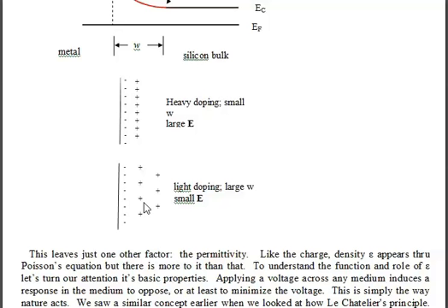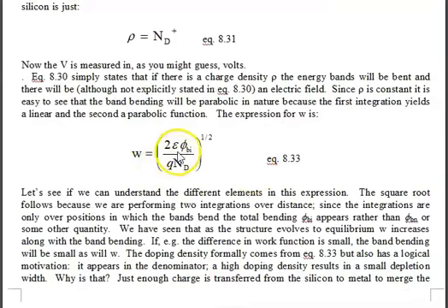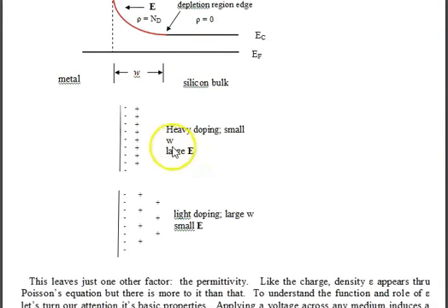What makes the electric field small? Permittivity. Because we know that with high permittivity, the silicon atoms here will polarize themselves, plus charge moving to the left, and minus charge moving to the right, which reduces the electric field. And the smaller the electric field, the larger the W.